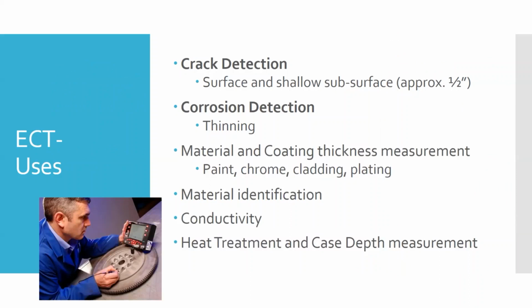So eddy current testing can have several uses. Probably the most common is crack detection. This is what's used typically for things like fuselage inspections to look for rivets that are starting to crack. This was that Aloha Airlines airplane where the top came off, part of the fuselage tore away. And so we do these kinds of inspections in order to try to find that. We also use it pretty extensively on internal engine components for turbine engines, and again, looking for cracking. So things like fan blades.